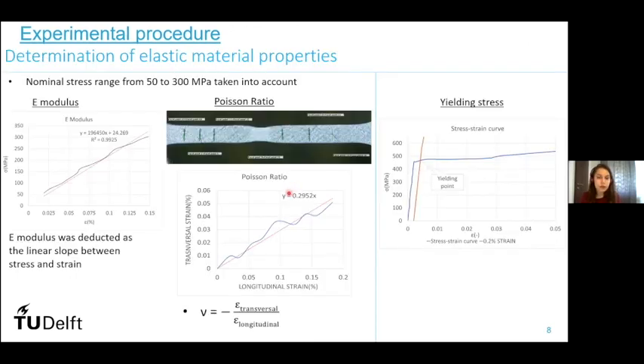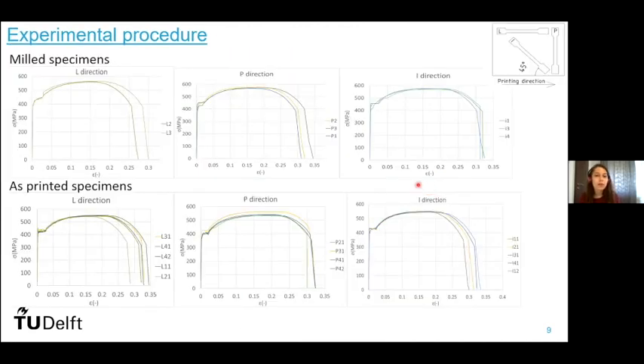To determine the elastic material properties, for the modulus and Poisson ratio, I used the nominal stress range from 50 to 300 megapascals, using a classic method of determining both ratios. E modulus I deduced as a linear slope between stress and strain. For the yielding stress, I computed the 0.2% strain with the slope, the E modulus that I extracted from the test. At the intersection between the stress-strain curve and the 0.2% strain line, I found the yielding point. Finally, I put together all the diagrams for all types of specimens that I analyzed, based on either they were milled or as printed specimens, and also based on the cutting from the plate alongside, perpendicular, or inclined to the printing direction. As you can see, for all specimens up until the ultimate strength, the diagrams were almost identical, and after that they start to be a little bit different.